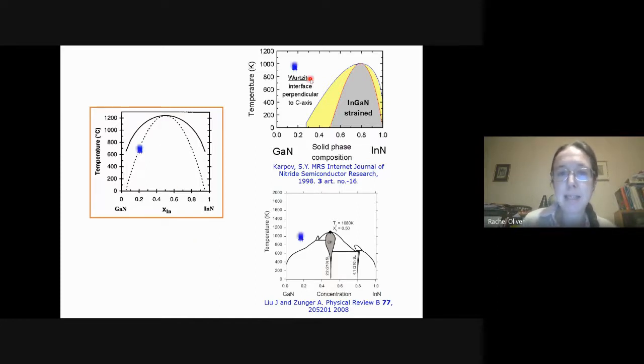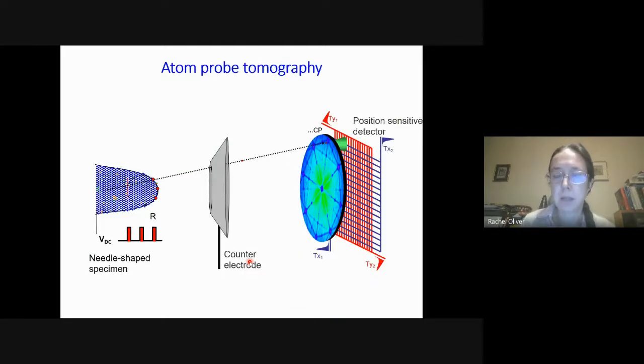My little blue LEDs here are representing roughly the temperature at which you grow indium gallium nitride in a standard commercial process in an LED. And what we can see is that the Ho and Stringfellow phase diagram does predict we split up into gallium nitride and indium nitride regions if we're at this composition and temperature relevant to LEDs, but the other two phase diagrams don't. They expect the material to stay as a random alloy. So the phase diagram analysis has at least shown us that there's a bit of a question here as to whether we'd expect this separation into gallium nitride and indium nitride rich regions and the formation of these indium rich clusters. So how would a metallurgist attack this problem experimentally?